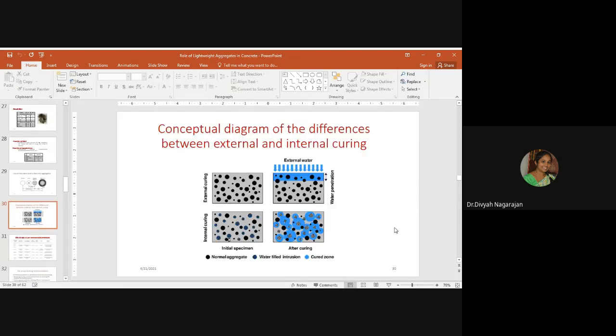Here is the conceptualized diagram for the difference between external and internal water curing. The complete hydration can be ensured only by adequate curing. We know that. The water absorbed during the initial stage by the porous aggregates helps the concrete to compensate for the moisture loss at later periods. Due to this unique feature, these concretes are less vulnerable to the lack of curing compared to normal density concretes. Apart from compensation for moisture loss, the existence of this absorbed water plays a major role in concrete.